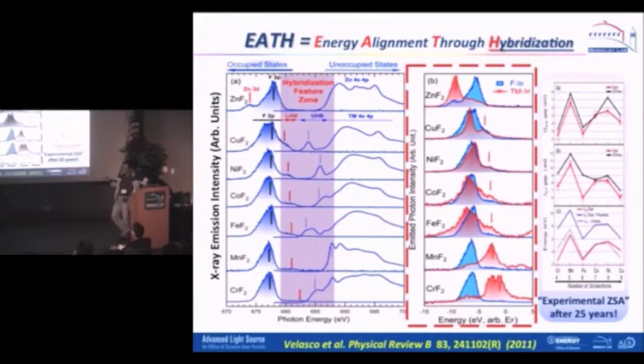Then our first problem is really whether we can use the soft X-ray to get this diagram out experimentally. And this is a set of transition metal fluorides. We choose it because it's a very ionic state, the same as the battery systems. What we see is this is the emission and this is the absorption. We see a bunch of hybridization features between the fluorine P and the D. By making use of these hybridization features, we are able to align the transition metal 3D and the anion P. You can see that all the 3D is sort of crossing this F2P level from the top to the bottom. That actually does map out the Zaanen-Sawatzky-Allen diagram.